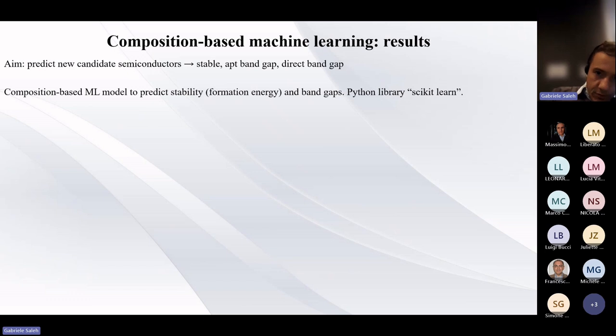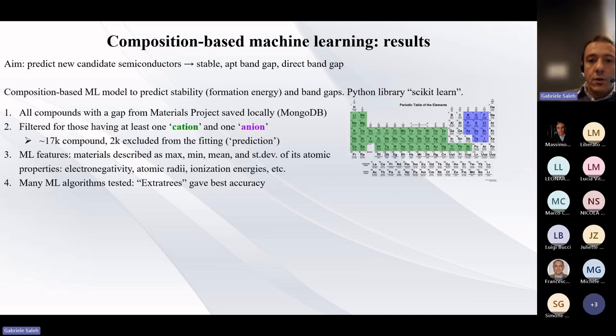Here we talk about formation energy. We implemented the machine learning framework in a Python code that uses the scikit-learn library. We started from the Materials Project. We took all the compounds which display a band gap, so they are semiconductors. We store them in a Mongo database. And then we filter them for those compounds that have at least one of these elements in green, which are typically cations, and one of these elements in violet, which are typically anions. We end up with about 19,000 compounds. We use 17,000 of them for training and test, and 2,000 for validation.